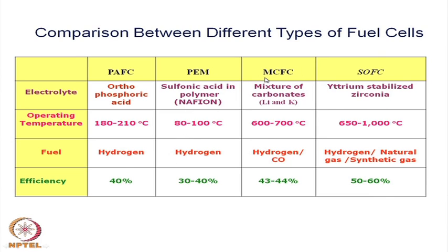In case of MCFC, that means the molten carbonate fuel cell, it is a molten carbonate, actually a eutectic mixture of lithium and potassium carbonate, which melts at a relatively low temperature, and that is the electrolyte where the carbonate ion is the conducting species. And the solid oxide fuel cell is basically, one can use calcium oxide no doubt, but as we have seen earlier, yttrium stabilized zirconia has a much higher ionic conductivity compared to calcium stabilized zirconia. So, although yttrium is slightly costlier, one can get the advantage of higher conductivity. So, yttrium stabilized zirconia is the standard material used as the electrolyte.